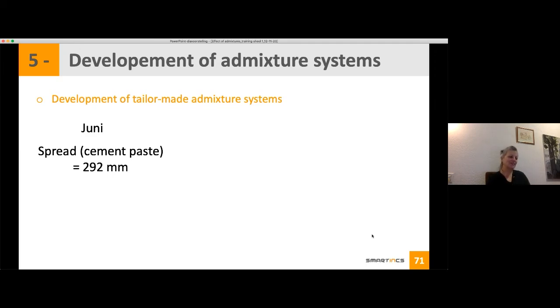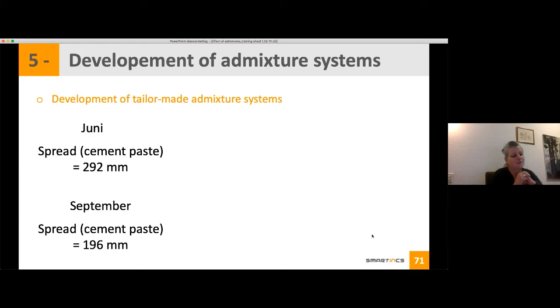So for instance, you have a case, and on the site, it was June, and they use a special workability admixture, and then they have a spread of 292 millimeter. It goes on, summer break, holidays, and then September, the same cement, same mix design, same admixture, and then suddenly the spread was much lower.